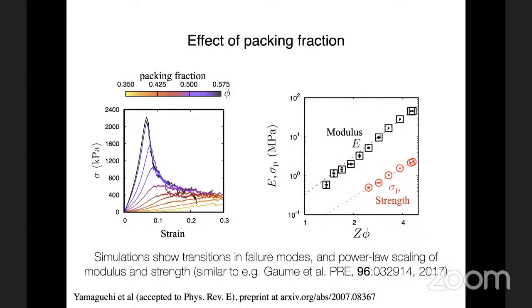Again, one of the more intriguing things, at least from my perspective, is that you can then measure how the modulus and the ultimate compressive strength depend on the number of contacts, or the density of contacts. I won't talk much about this due to the shortness of time, but this relates to some work that is underway recently about how stress chains affect the scaling of the material properties of things like sandstone or sticky spheres. Baxter's sticky spheres is one of the models used for this. And these predict very high power law dependencies of properties like the elastic modulus or the ultimate compressive strength on the density of contacts, which is consistent with what we're finding in the numerics.